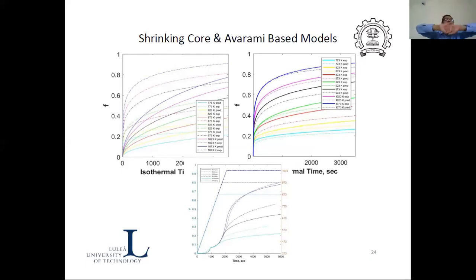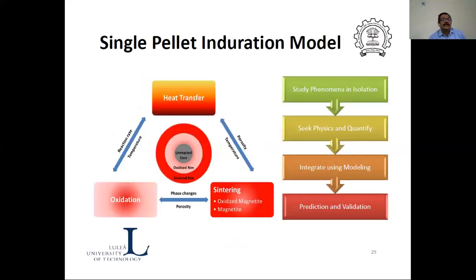Now we can combine these two, because sintering affects the oxidation: once the sintering happens, the voids get closed, so the gas cannot reach. And of course, depending on whether it is magnetite or oxidized magnetite, the sintering is going to change. So oxidation is going to get affected by sintering. Hence now, once we know them in isolation, we can use the principles of modeling to integrate. And that's what we did. And of course there is an associated heat transfer. So now we use the principles of modeling, and we can predict.